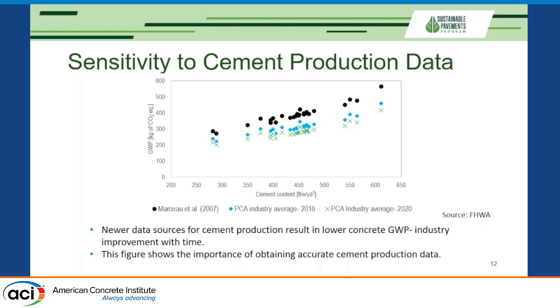And we can see that PCA's industry average from 2020 is at the bottom, and then we have higher impacts when we use PCA industry average from 2016, and yet the highest impacts when we're using this study of Marceau et al. from 2007, which was the predecessor to all these PCA studies. Overall, this is a good trend because it shows that overall cement industry is improving.